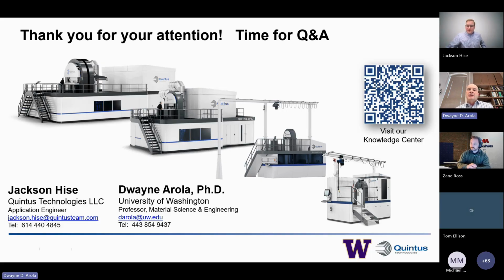Yes. Jessica asked, how did the team control loading in the stress relieving and HIP? Was everything kept on the plate? Actually, to be able to reduce shipping efforts between the partners, the individual groups or clusters of specimens were sectioned from the plate, and then they were heat treated, combined in those particular clusters. We heat treated all of the clusters for each partner together. That means contained as if it came off the build plate, but the individual build plate sections were removed.